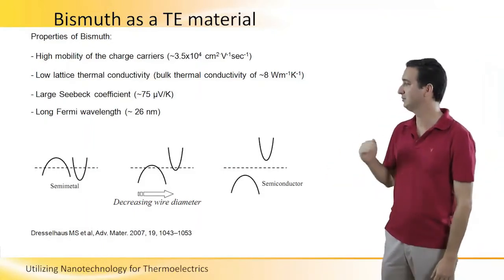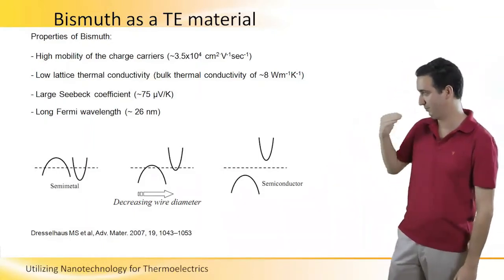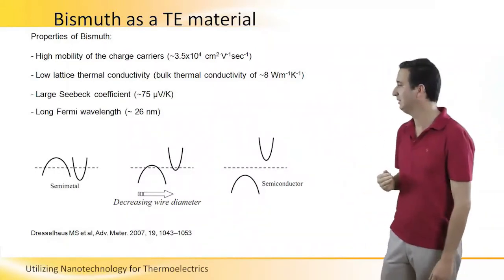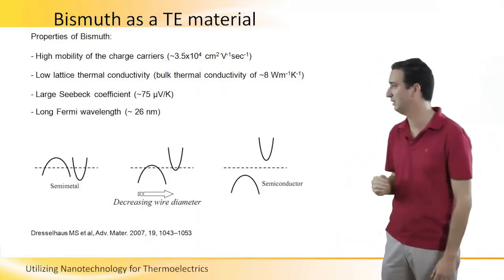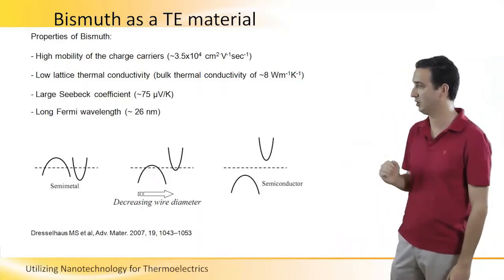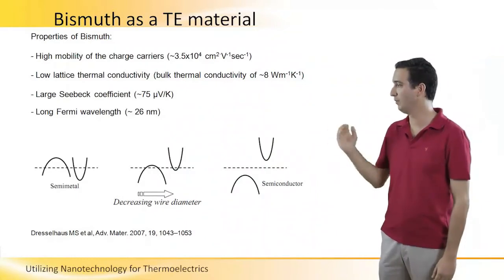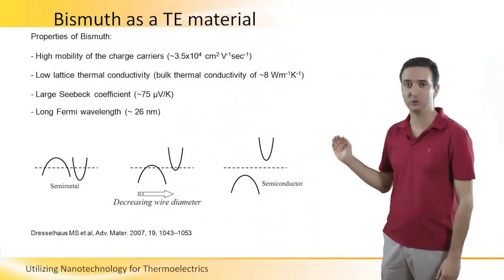The reason for the high efficiency of Bismuth as a thermoelectric material - there are a few reasons due to its characteristics. For example, the high mobility of the charge carriers and the low lattice thermal conductivity.